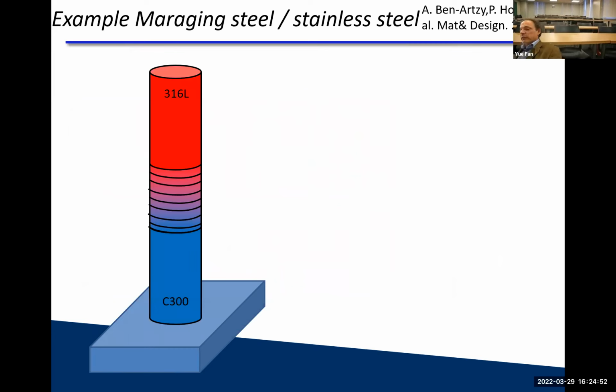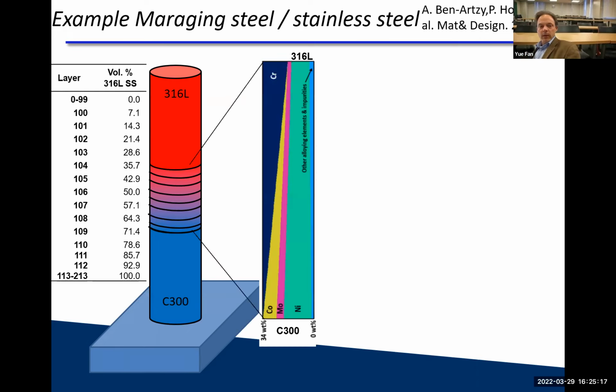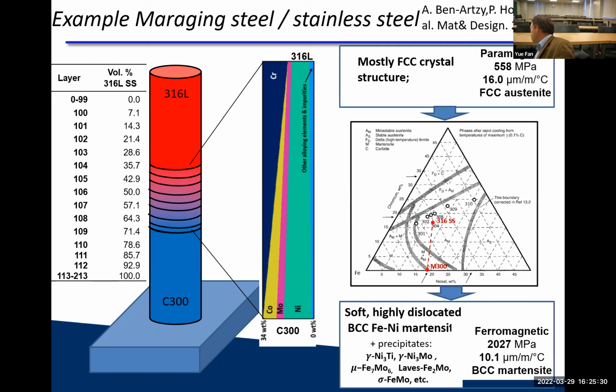In fact, that particular project was inspired by JPL, as you saw earlier on the logo, and they were interested in doing something like that for space vehicles, because there's very limited space. You can't make too many connections. That's very interesting to see if you can grade something. So we printed maraging steel C300 to 316 and did a layer-by-layer gradual change of the composition. As you can see, it's 100-some layers, and you change the composition along the line. The powders were pre-mixed, so you change the composition gradually. Okay, so far so good.